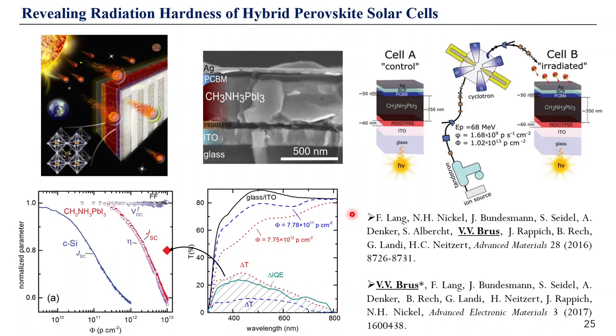So my first contribution in the field of radiation-resistant photovoltaics was done during my stay at Helmholtzzentrum Berlin. There we have shown that hybrid methylammonium lead iodide perovskite solar cells, regardless of their known photoinstabilities, reveal much higher radiation resistance in comparison to their silicon counterparts. So that finding was quite influential in terms of development of research activity in the field of single junction perovskite and also CIGS perovskite tandem solar cells for photovoltaics around the world. Now this direction is actively under development and research.